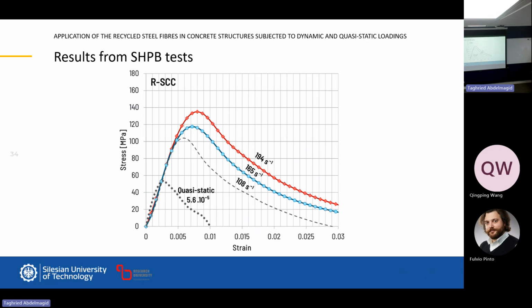And what did we achieve for the fiber reinforced concrete with the usage of recycled fibers? Here is the typical diagram. And this is the comparison with quasi-static, the stress-strain relationship. When we increase the strain rate, of course the strength increases, and it's comparable. The results are very similar to the results of other kinds of fiber reinforced concrete.